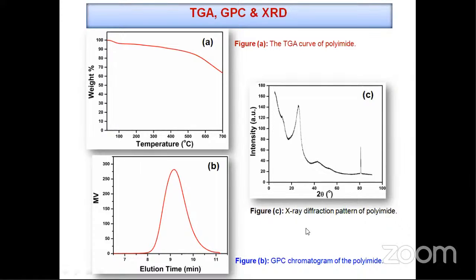The morphological behavior of the synthesized conjugated polyimide can be studied with the help of the XRD pattern. Here, this figure represents the XRD curve of the polymer. In the XRD curve, a broad peak appeared between 18 to 38 degrees, which indicates that the synthesized polyimide is amorphous in nature. Some small peaks also appeared, which give the semi-crystalline nature also.